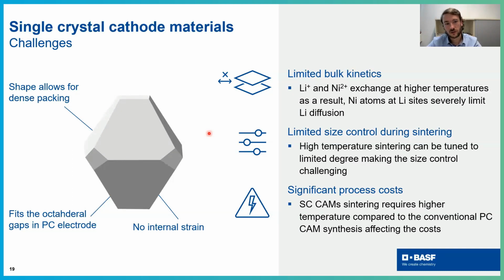Then another thing, if you have additionally the nickel and lithium sites intermixed within the lattice, then you have even more problems kinetically. Another challenge of these materials is that you typically use high temperature sintering, and if you do that, then it is not always easy to size tune these materials because you have temperature variations and the size is very sensitive to the temperature, especially at large scale. And for sure, if you go to high temperatures, it's more expensive. So single crystal materials are typically more expensive than the polycrystalline ones.